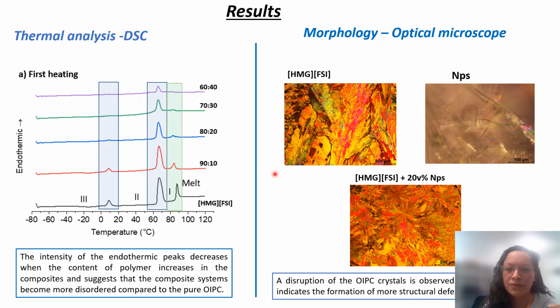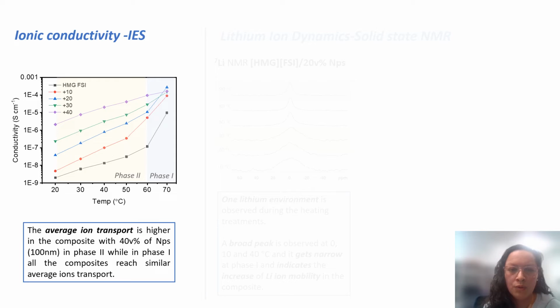These results were confirmed with the optical microscope, where we observed in a composite with 20 volume% of nanoparticles that the crystals of the organic ionic plastic crystals are disrupted, which means we are creating more structural defects in these materials. We measured the ionic conductivity of these materials, and we found that in general the addition of polymer nanoparticles increases the ionic conductivity, and also that the composite with 40 volume% shows the highest average ion transport.